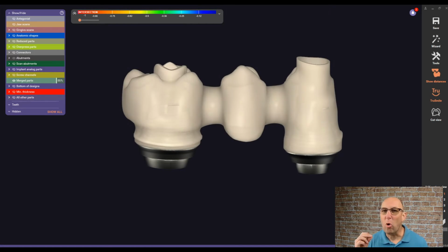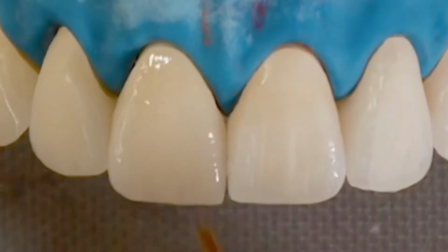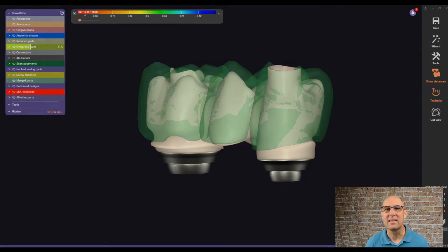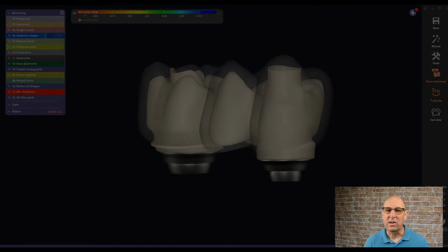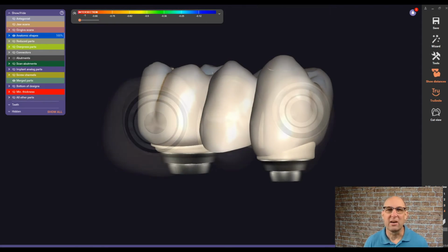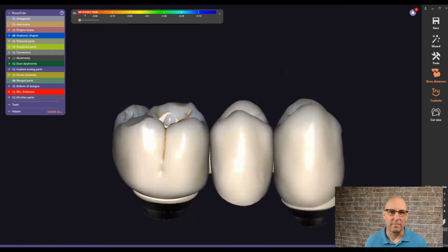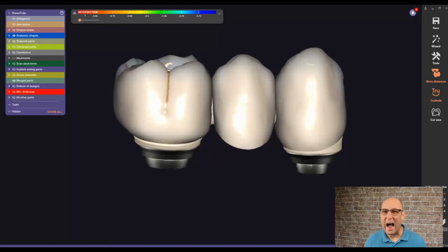Then opaque it and overpress it in porcelain. If you haven't seen my video on how to contour teeth, I highly recommend that you watch it now. After you glaze the restoration, you have to cement the Ti-Bases into the metal framework. Make sure you don't do it before, because otherwise the cement is going to burn out. Of course, you can also layer the porcelain onto the framework, but I recommend to overpress it.